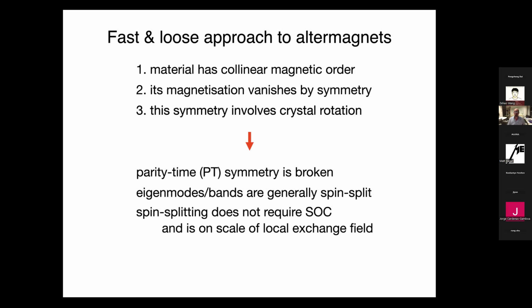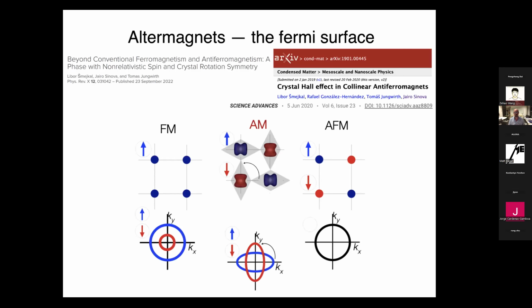Okay. The consequence of these three facts is a breaking of parity time symmetry, so a spin splitting of the bands in general. This is not only true for electronic bands, but it is equally true for magnon bands, for the magnetic excitations of the system. Also, those bands are generally spin split. Important is, as I said before, that the spin splitting does not require spin-orbit coupling, and it is on the scale of the local exchange field, which is a large number, for instance in 3D transition metal oxides, a number that in general is much larger than the spin-orbit coupling.